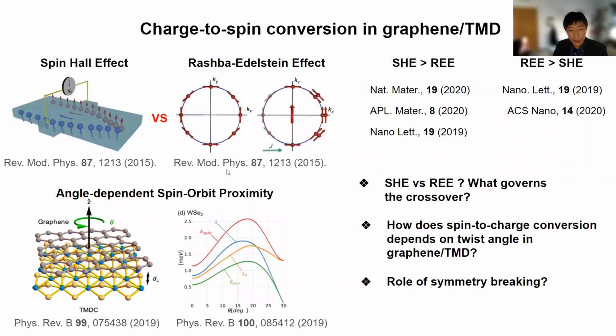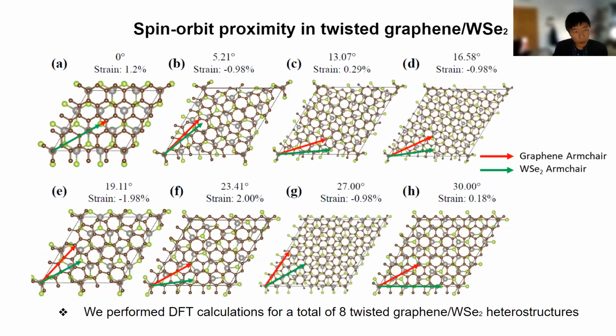So there have been a couple of experiments on twisted graphene on TMD, and the experiments observed both the spin Hall effect and the Rashba-Edelstein effect. There is a group of papers that observe a larger spin Hall effect, and a group of papers that observe a larger Rashba-Edelstein effect. So what we want to study in this work is to look at both effects, and try to understand what might be responsible for the crossover between these two mechanisms, and also the role of twist angle. So how do we approach the modeling?